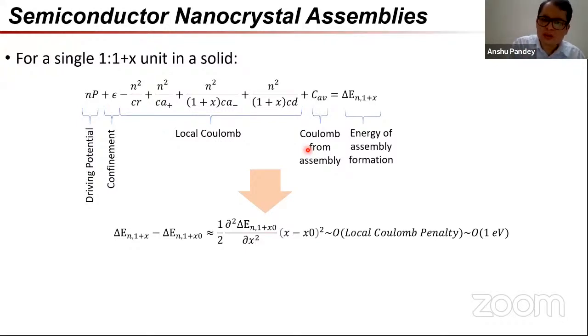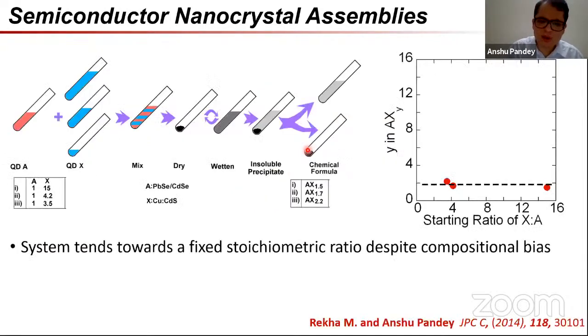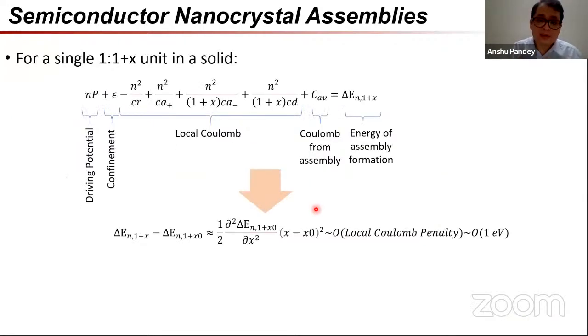So now we tried in our simple minds to reason out what could be happening over here, because there are not many reasons why stoichiometric ratios could emerge between nanocrystal types. Very simply, they cannot emerge because nanocrystals, while one would say they are called quantum dots, are not really very quantum at all. And confinement or quantum mechanical effects, which play a role in conventional chemistry, don't really work here. So rather, what we at least hypothesized was that this was a Coulomb effect.